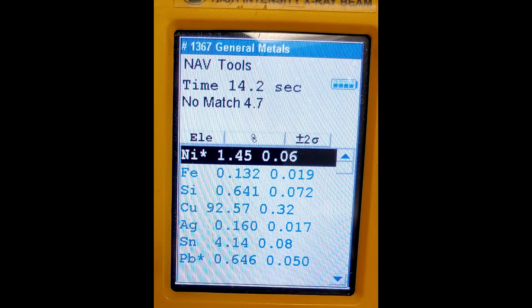Here's the second button we did with the copper oxide, and you can see immediately that the copper percent went up. It's about 92.5% now. But interestingly, the nickel was pretty much untouched. The nickel hasn't been affected at all. The iron has been reduced effectively to 0. Silver is still there in about the same concentration. Tin has been reduced by half, and lead has also been reduced by about 75%.